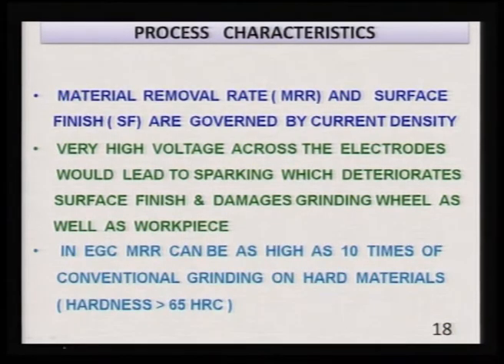In case of electrochemical grinding, it should be ECG, not EGC. MRR can be as high as 10 times of conventional grinding on hard materials. Materials having hardness greater than 65 HRC can be machined by this one, and 10 times greater MRR is a very high value compared to conventional grinding. So, this is an additional advantage of electrochemical grinding.